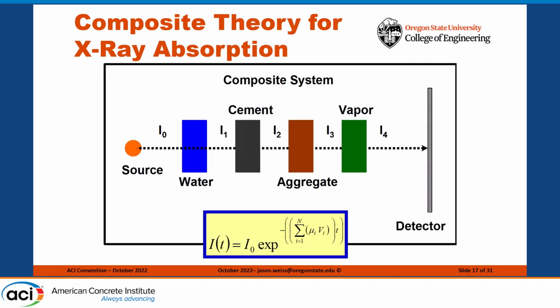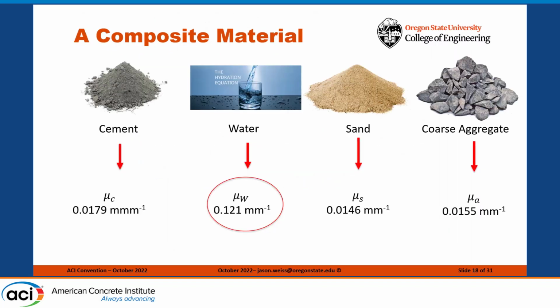But it gives us the ability to quantify the exact amount of water with high precision at high spatial resolution. We can get down to about 50 microns. Some of the best systems in the world get down to about 10 microns. After that, you really start pushing the limits of X-ray physics without doing something very special.